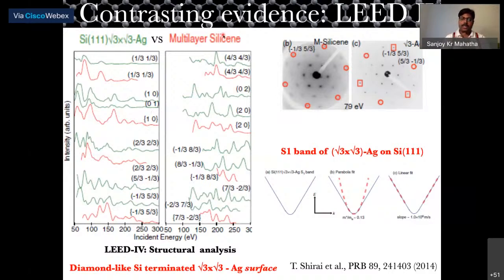One is multi-layer silicene, prepared in the same way the other group claimed. The other structure is the root 3 by root 3 silver structure on top of silicon. As I said, multilayer silicene has a root 3 by root 3 structure. So this one is silicon on top of silver, and this one is silver on top of silicon. These are two different systems, but pretty similar, and if you follow the LEED IV curves, they were quite similar. Then they claimed that this multi-layer silicene structure is pretty close to that of silver on silicon.